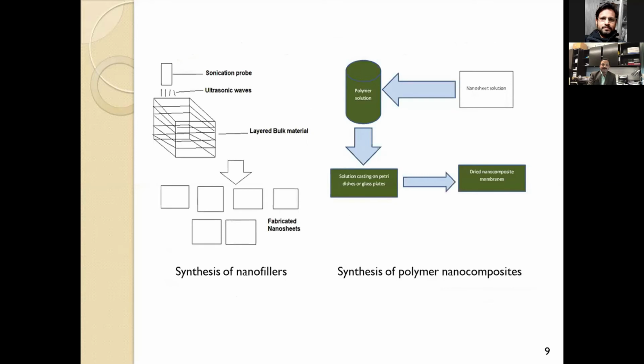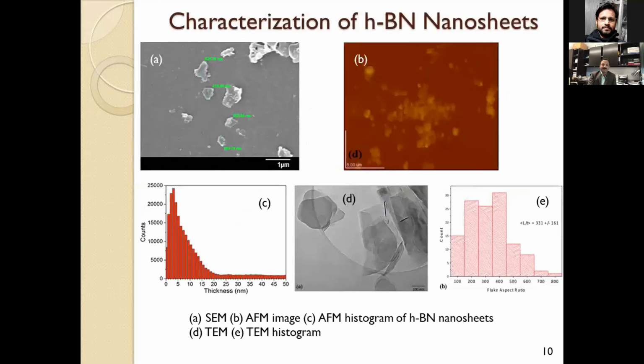This is a schematic diagram of how nanofiller is synthesized and how the nanocomposite is synthesized. Now, after synthesis comes the characterization process. For the characterization, we use three main methods: AFM, that is atomic force microscopy; SEM, which is scanning electron microscopy; and TEM, which is transmission electron microscopy. In the SEM, we can see that the flakes have lateral dimensions of about 0.5 to 1 micron.